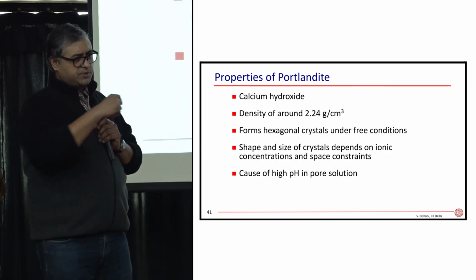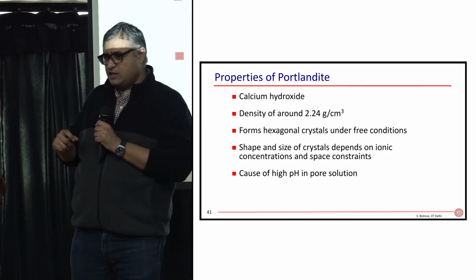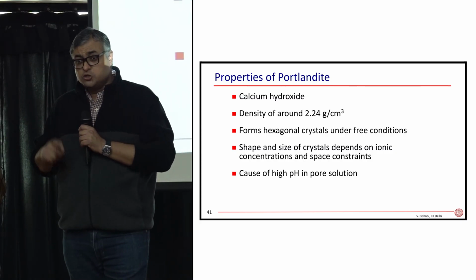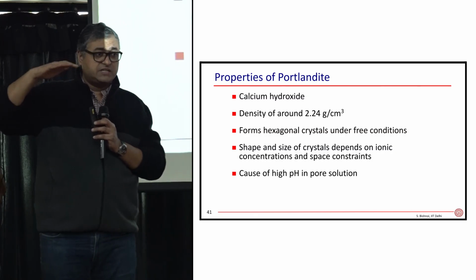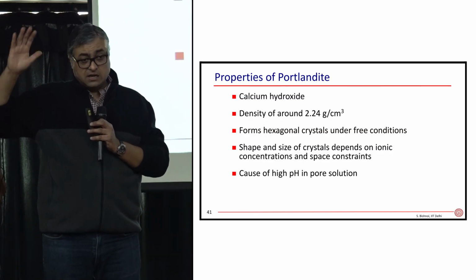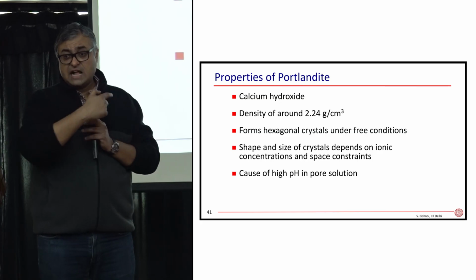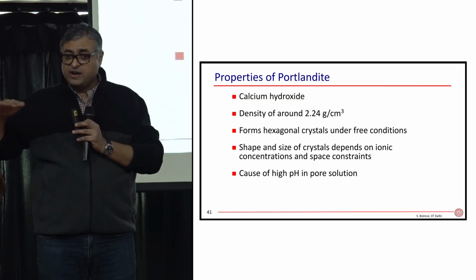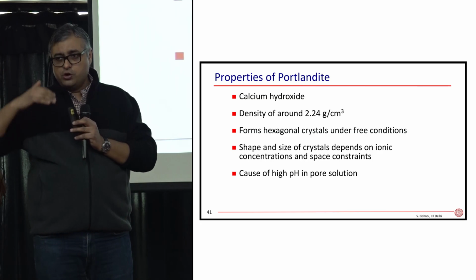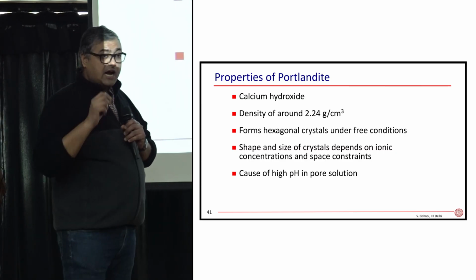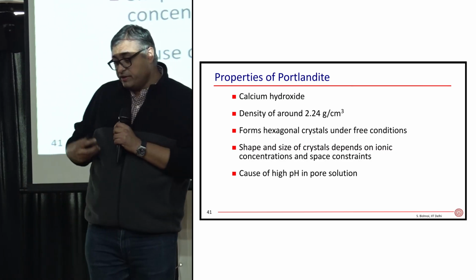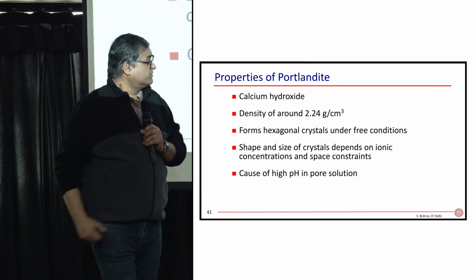When I showed you the composition of cement, something we skipped over was that they also contain sodium and potassium. The sodium and potassium maintain a high pH inside cement, above 12, 13 of that range. This calcium hydroxide is buffering that solution, making sure you're maintaining a high pH, and that protects the steel inside the concrete. We're able to make reinforced concrete because of that.